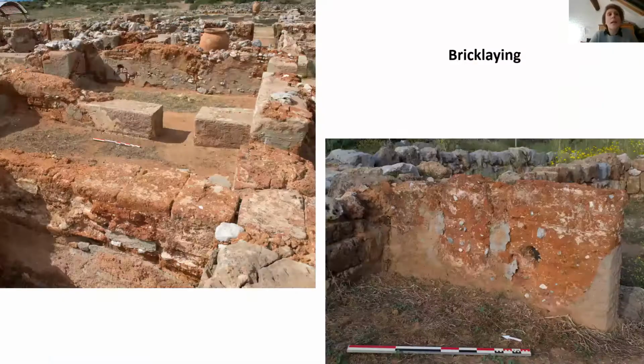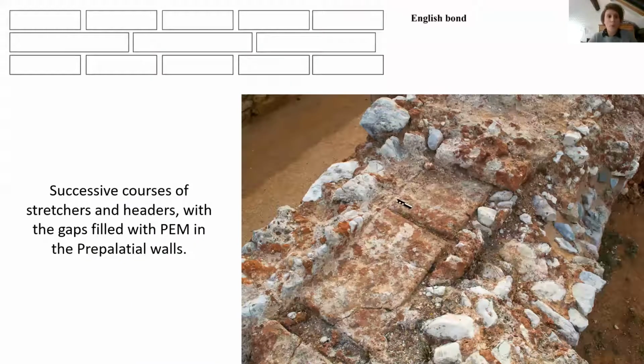In most cases, the mudbricks are laid in header bond, which means with one of their shortest sides on the wall face. But running bond, that is with the mudbrick set in stretchers or with one of the longest sides on the wall face, is common in partition walls. It also regularly happened that the builders set bricks in a different position from the most common bricklaying to better fit the dimensions of the wall, so that it is not uncommon to find mudbrick specimens set upright in the wall. There is also one example of English bond with successive courses of headers and stretchers in the north wall of the pre-palatial Kazmat. And as you can see on the illustration, the gap between the courses is filled with plastic earthen material with small stones.